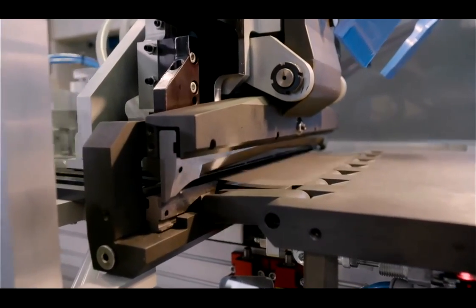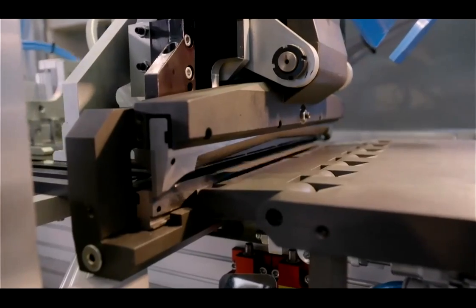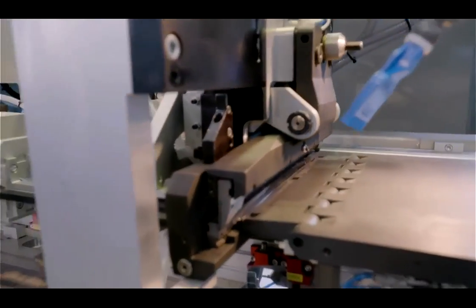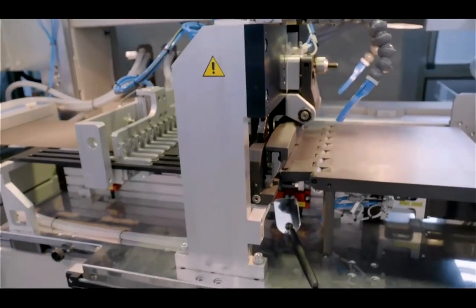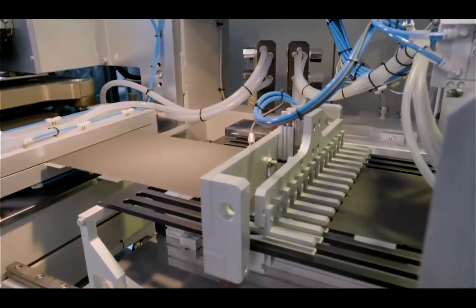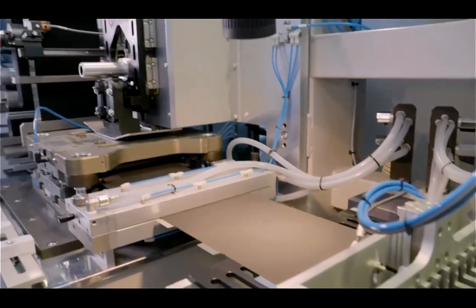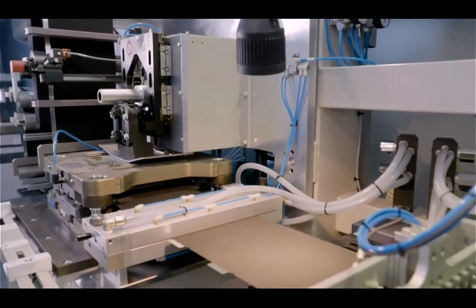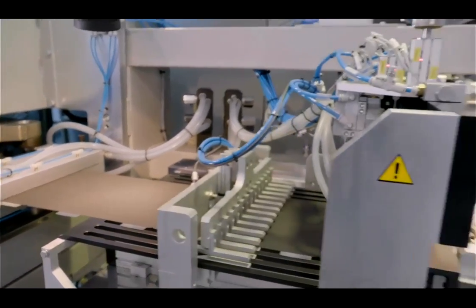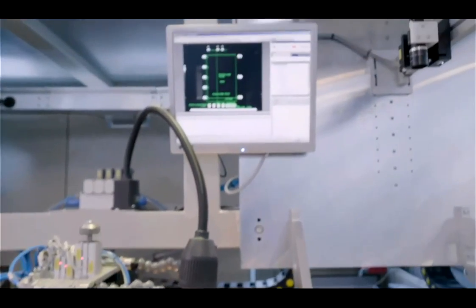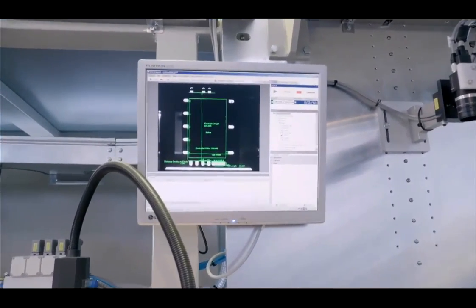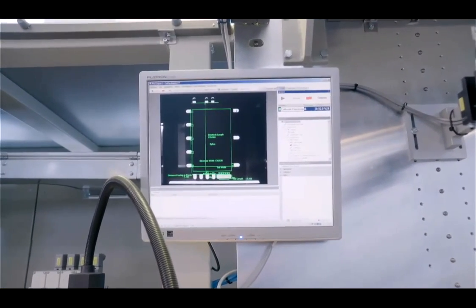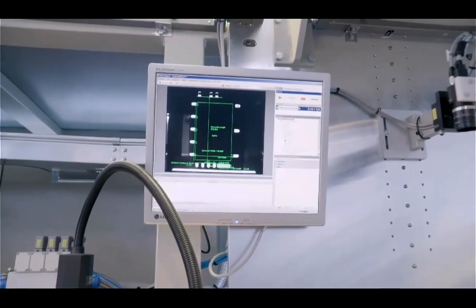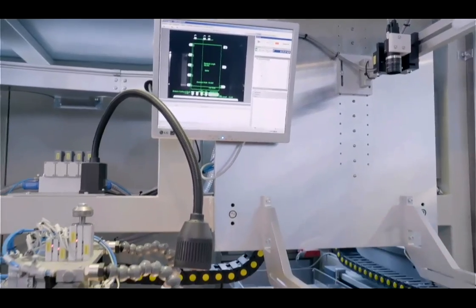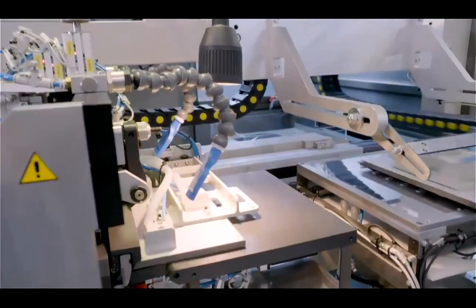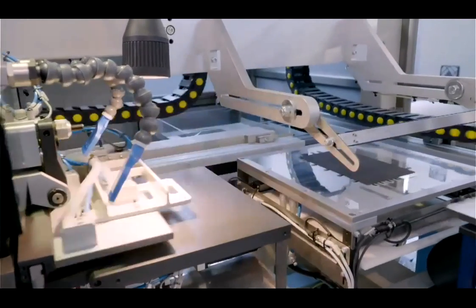Okay, so you are seeing now that the sheets are positioned using a vacuum gripper. Some process parameters for this machine: we are able to cut around 20 electrodes per minute. The tolerance requirement that we have is 100 microns for the length of the sheets. Here you see the inline quality control we have. We take a picture of the sheet, and we have to control that the dimensions of the electrode are okay. We check that the position of the tab is the correct one, and we check that the distance between the tab and the edge is the correct one.